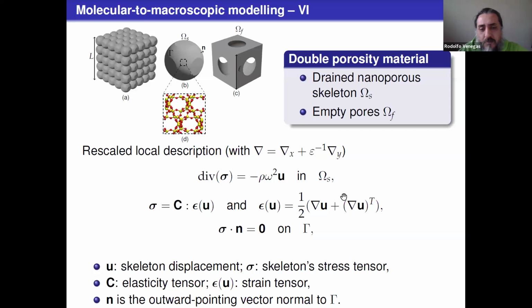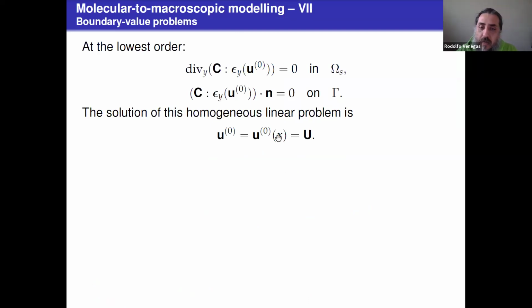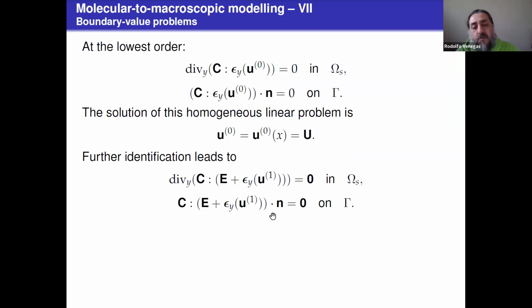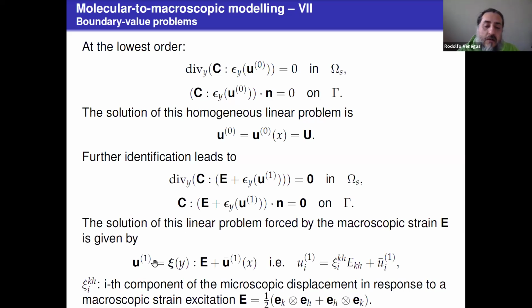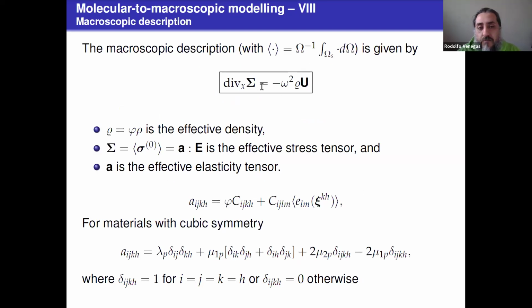So we start with the equation of conservation of momentum and this constitutive law. We consider linear deformation and no normal stress on the surface of these nanoporoelastic spheres. Applying homogenization, we get that at the lowest order the displacement is a macroscopic variable, so it only supports rigid body motion. Then we get the corrector for the displacement by solving this linear problem that is forced by the macroscopic strains. The solution is an operator, a third-rank tensor acting on the macroscopic strain. After that, we get the macroscopic description, which is a classical conservation of momentum equation, where sigma is the effective stress tensor, which depends on the macroscopic strain and the effective elasticity tensor.